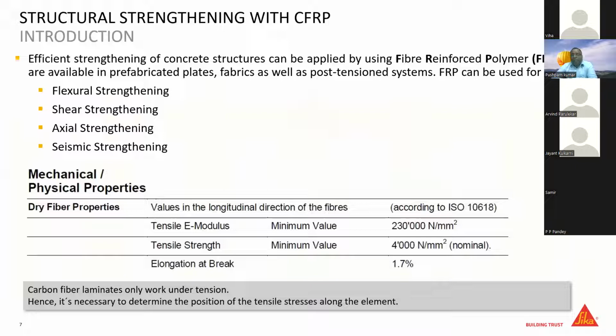These carbon fiber materials have high mechanical properties. I would just like to make a comparison with steel. Fe 500, which we use, has a tensile strength of 500 MPa. When you compare with CFRP, this carbon fiber material has a tensile strength of more than 4000 MPa. So roughly around 8 times higher tensile strength compared to normal steel.